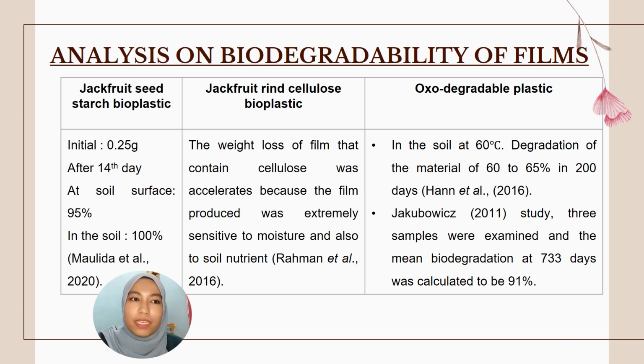For the jackfruit rind cellulose bioplastic, the weight loss of the film containing cellulose was accelerated because the film produced was extremely sensitive to moisture and also to soil nutrients. For oxo-degradable plastic, in the soil at 60 degrees Celsius, degradation of the material was 60 to 65% in 200 days. In another study from Jacobowitz in 2011, 3 samples were examined and the mean biodegradation at 733 days was calculated to be 91%.